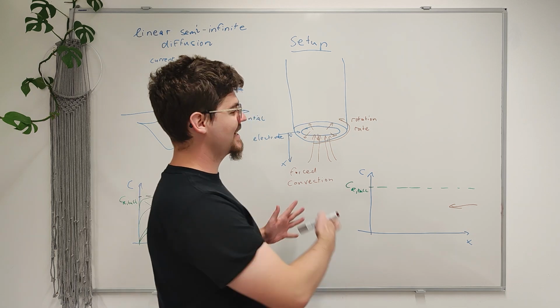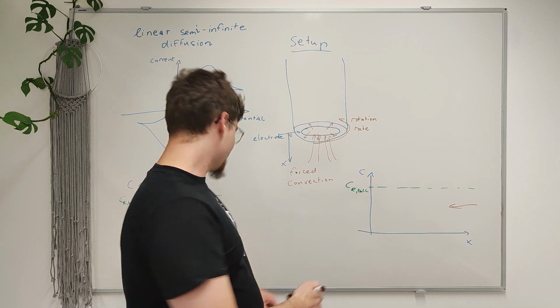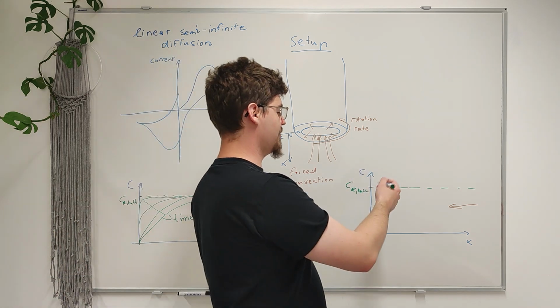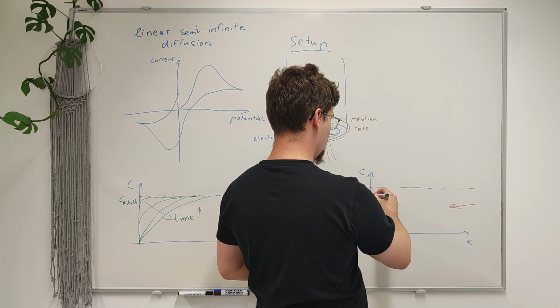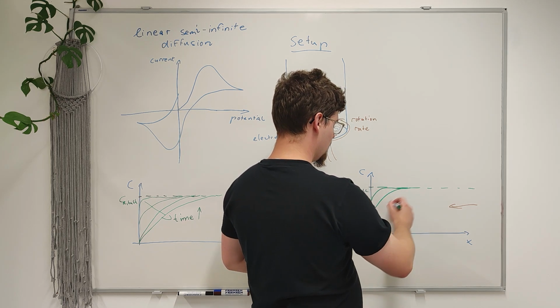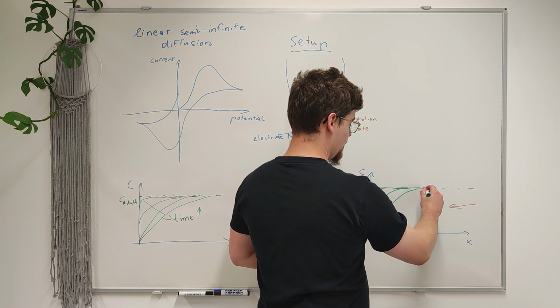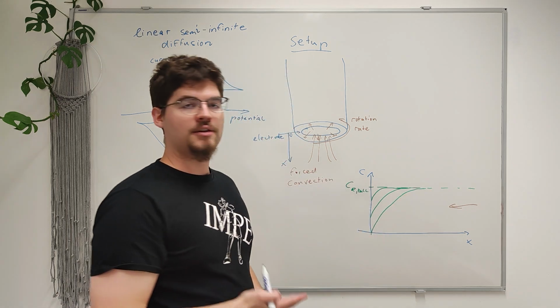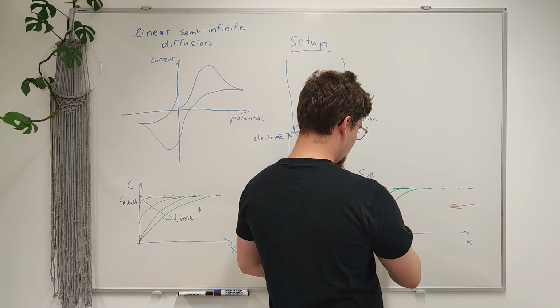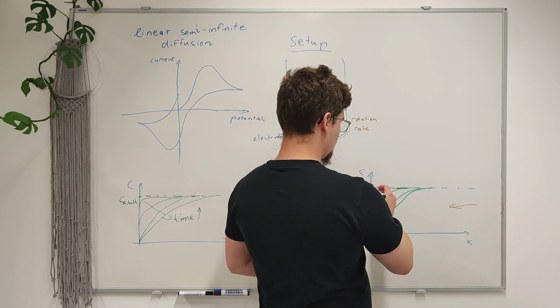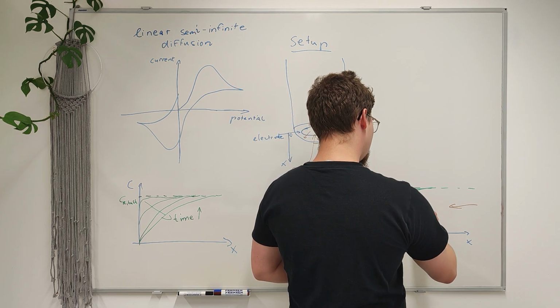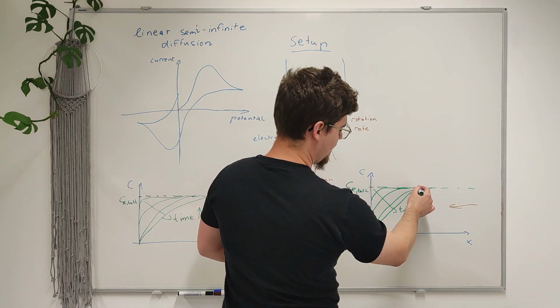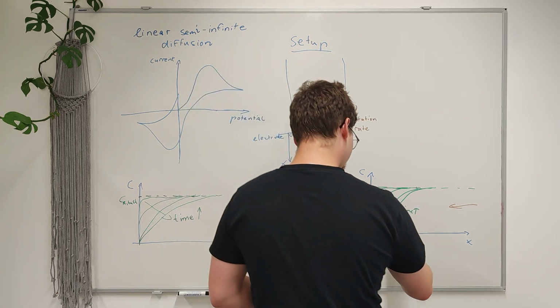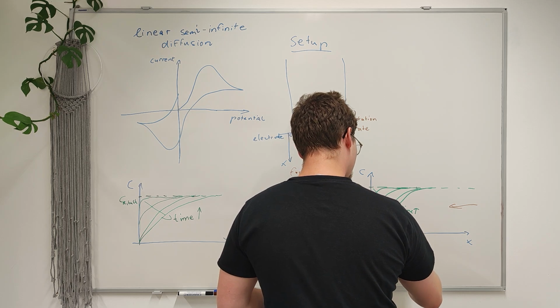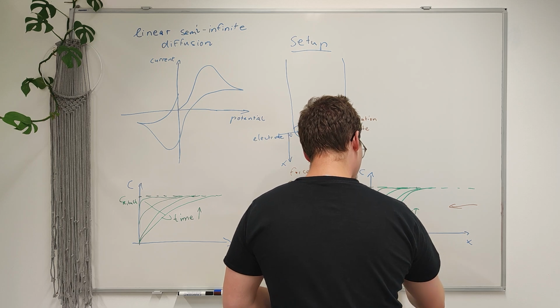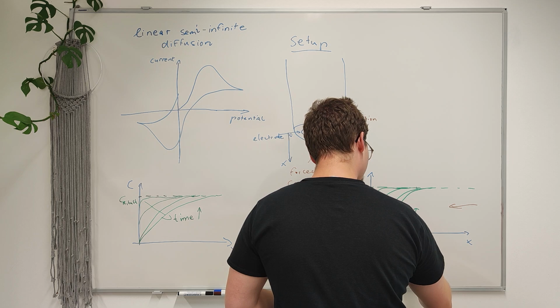What this means is that the diffusion layer can no longer extend as far as it once did. In fact, we apply a potential and initially the concentration at the electrode decreases as well. But we reach a point where, due to this replenishment of the electrolyte, the diffusion layer can extend no further. So as time increases, we get a constrained diffusion layer thickness. Let's call this here diffusion layer thickness, delta.